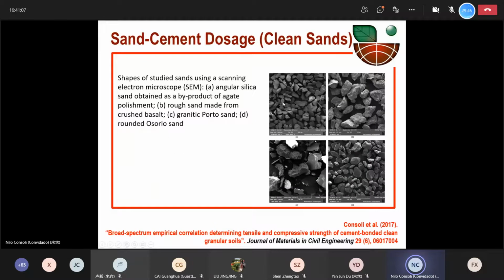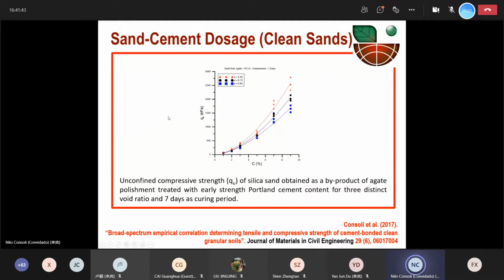Another quite interesting thing that we published in 2017, also in the Journal of Materials in Civil Engineering, was that different sands, and we can see here that the shapes and the roughness are different, and they are even from different places, this one from Portugal, this one from southern Brazil, and these are even residues with different shapes. But in all these cases they are fine-grained sands. We carried out tests with different void ratios, different amounts of cement, different cements, different curing periods, and both compression and tensile strength.